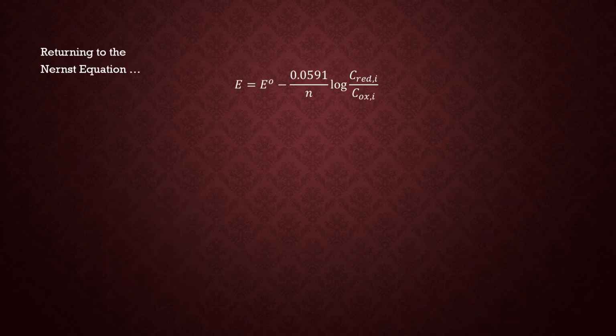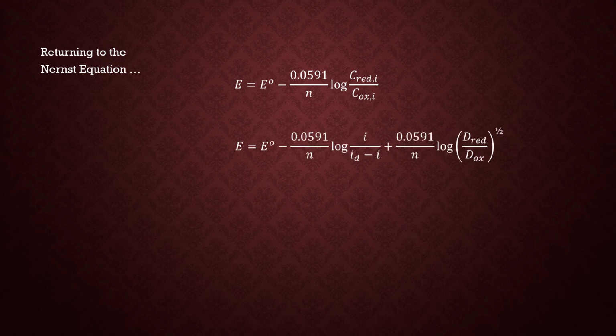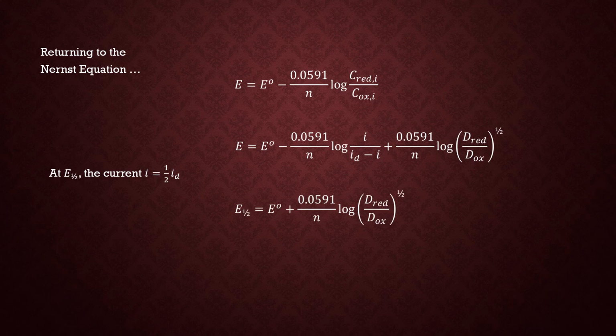So I do that now. I return to the Nernst equation and substitute the two concentrations from the previous slide. I get one log term expressed in terms of the current, and the second expressed in terms of the diffusion coefficients. When I look at the specific case where the current is halfway up that ramp, namely one half the diffusion current, and substitute this into the Nernst expression, that first term disappears, leaving me with just the Nernst expression in terms of the diffusion coefficients.